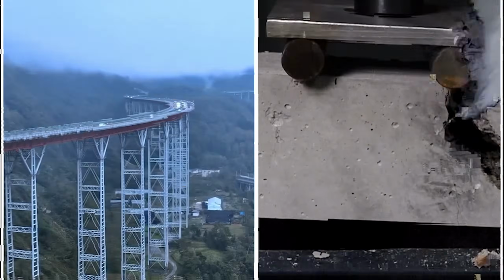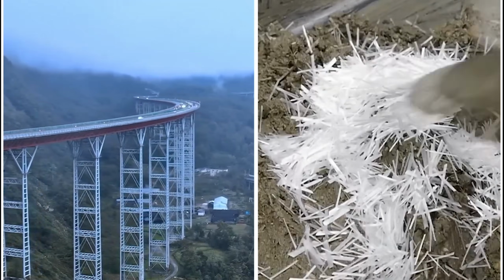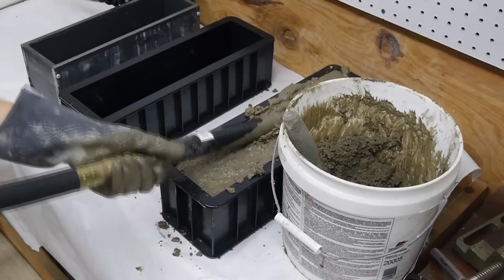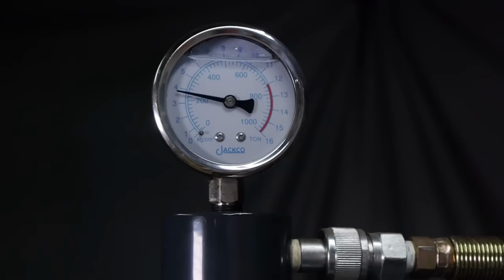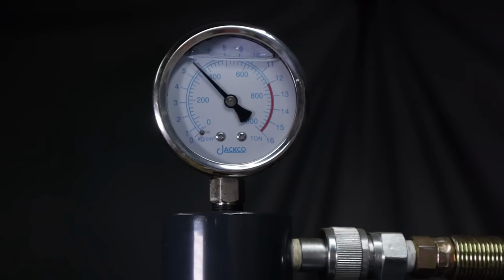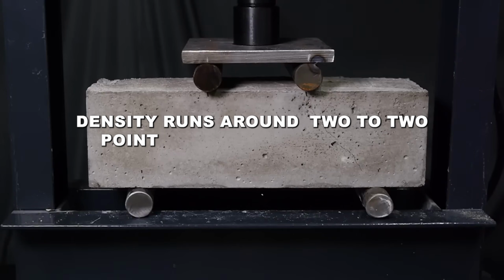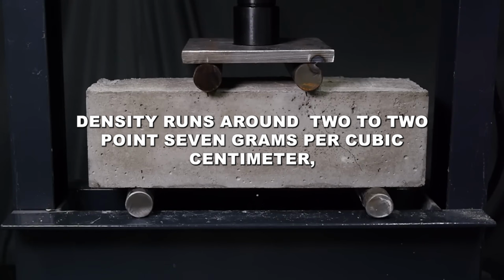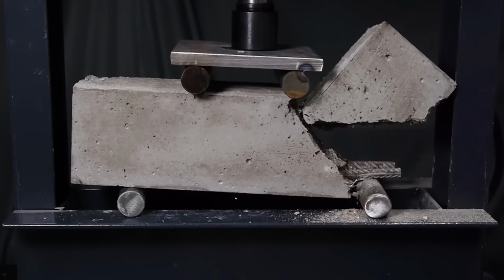It manages that while weighing about a quarter to a third what steel weighs for the same size bar, which means lighter trucks, easier handling on site without mechanical lifting equipment, and less dead load on the finished structure. Density runs around 2 to 2.7 grams per cubic centimeter, against 7.85 for steel.